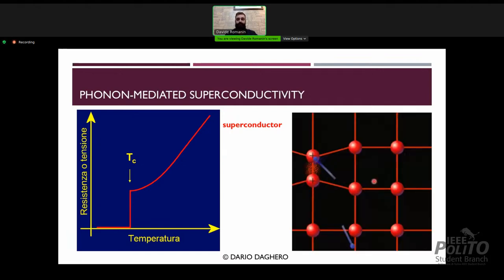Moreover, in phonon-mediated superconductors, we have an interaction between electrons. Here in this GIF, there are the blue spheres, which interact with the underlying vibrating lattice, here the red dots. Now, the normal modes of the vibrating lattice are called phonons, and two electrons can exchange a phonon in order to form what is called the Cooper pair. Now, the Cooper pair has an extension which can be very large with respect to atomic distances, and this is called coherence length, which is nowadays exploited for circuits for quantum computers, for example.